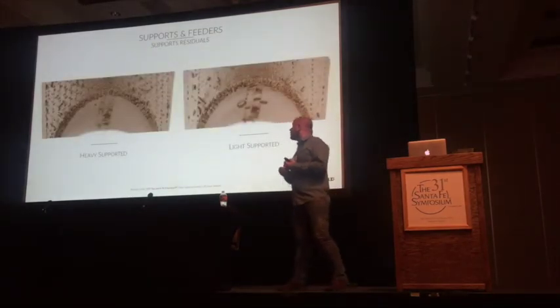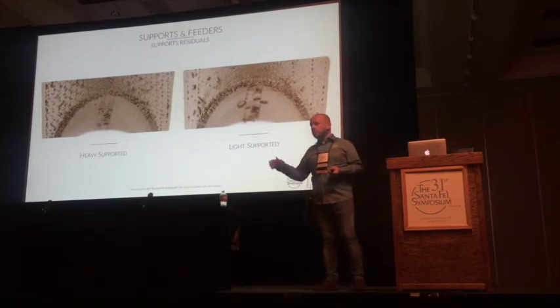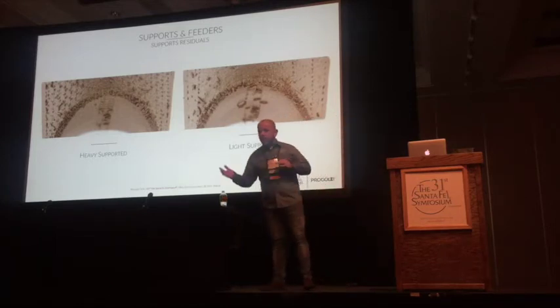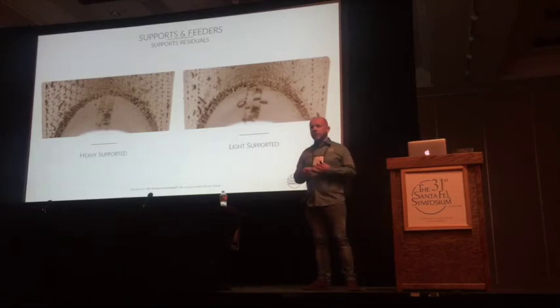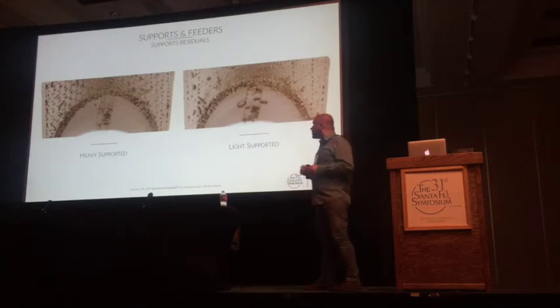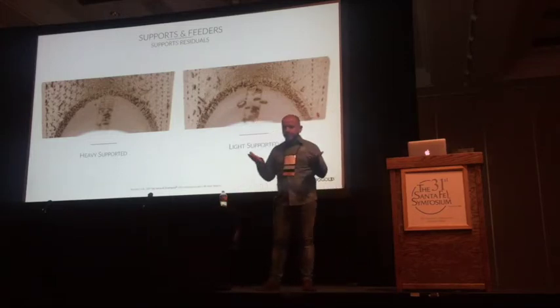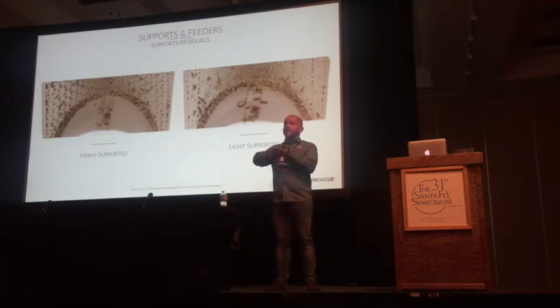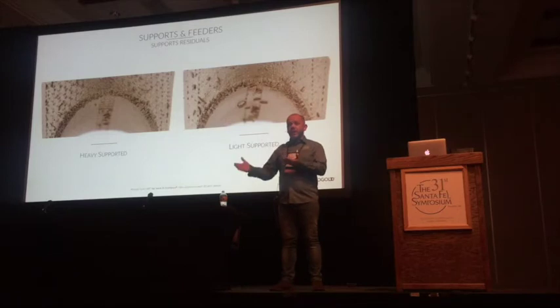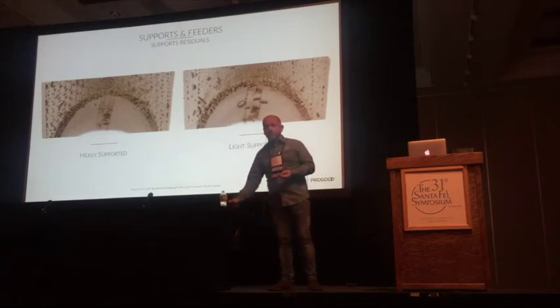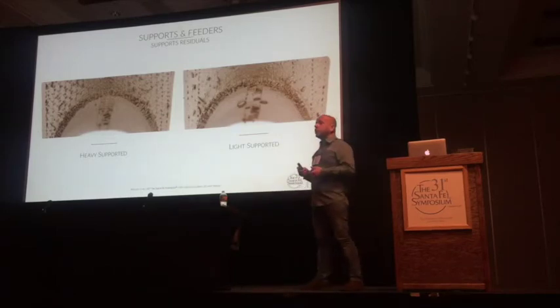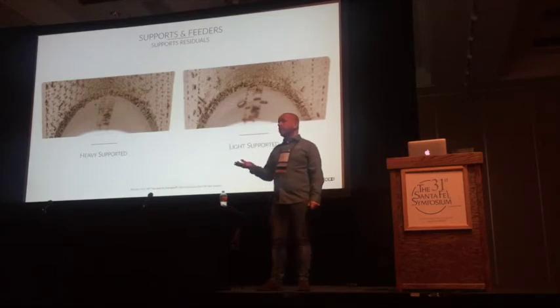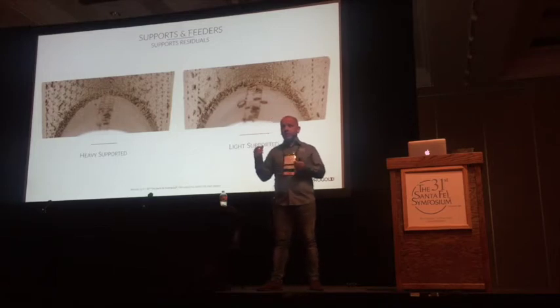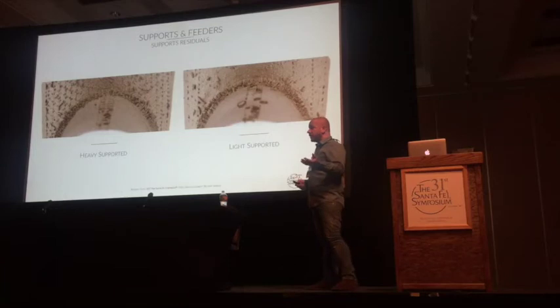Here we have an example of a typical surface when you have heavy supports or light supports. What is the difference in deciding to have heavy or light supports? That is a matter of practice, trying to figure out which is the lowest quantity possible. But a big difference between casting and 3D metal printing is that in casting, if you have very heavy rings and a sprue of 5 millimeters, then you have to reshape the surface. In this case, the surface is still there, and you just remove the supports, which are quite small. Anyway, the people in high-end jewelry don't care very much, because they have to take care of the pieces one by one, grinding with a micromotor, and it's not something done automatically.